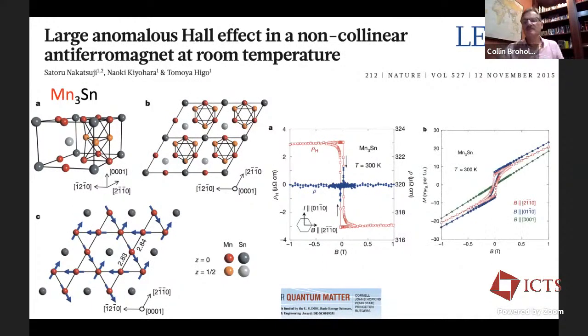And this notably occurs in the absence of significant uniform magnetization. Though there is hysteretic in-plane magnetization, so there is some small spontaneous moment that you can deduce from this, but it's on the scale of milli-μB per formula unit.